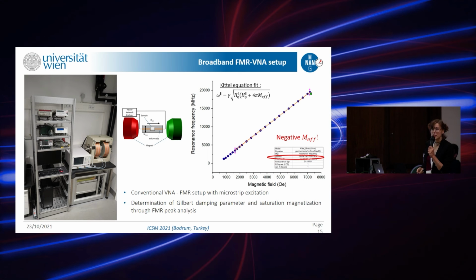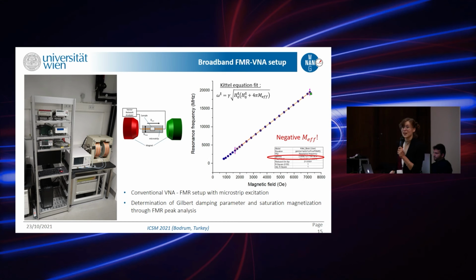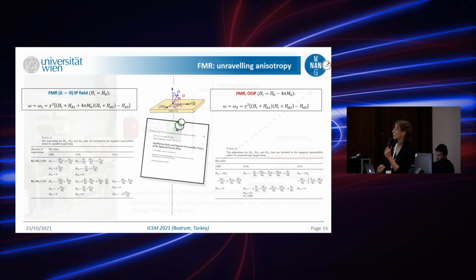Just naively fitting with the Kittel equation for the in-plane case, what you will see is negative effective magnetization. What does this mean? Effective magnetization is hiding saturation magnetization and anisotropy terms. Originally for YIG they are small, 30 for uniaxial and 50 for cubic. Here it means that these anisotropies are so high that they are overshadowing our saturation magnetization. Hence, a stronger theory is required to describe our materials.